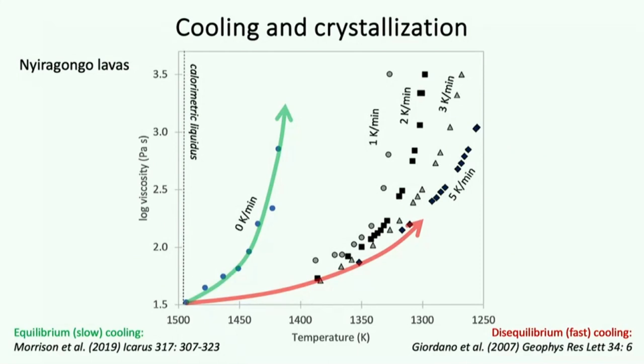Then we can also do experiments in the lab where we either measure the rheology isothermally, meaning we just leave it at one temperature and then maybe go to another temperature and wait for it to equilibrate there, or we can do dynamic cooling, which just means cooling, where we allow it to crystallize as well. And so here, if we were to take the liquid and cool it very quickly so that it couldn't crystallize, it would come along here where that red arrow is, and it would come through somewhere over here. It would stay pretty fluid until it approached the glass transition, and then the viscosity would increase rapidly. But if we cool it slowly so it can crystallize along the way, then we get a bunch of intermediate behavior depending on what the cooling rate is. And if we cool it really slowly, like a pluton, then it will always have the equilibrium crystal fraction, and actually the viscosity increases very quickly at a much higher temperature.